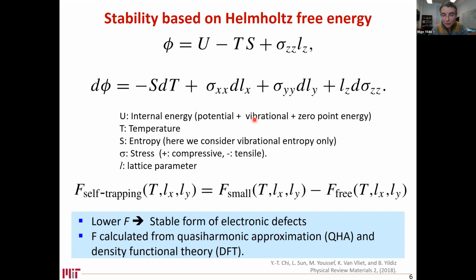So using the Helmholtz free energy calculations for the two different systems where we stabilize the free electron and where we stabilize the small polaron, we can look at the difference of these free energies and calculate the self-trapping energy, that is indicating the relative stability of the small polaron, or the trapped electron. And the lower the self-trapping energy, the more negative it is, the more dominant that defect will be.